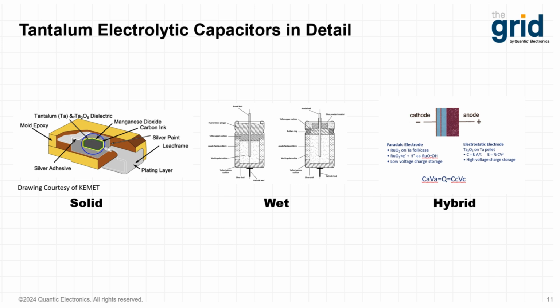However, there are some styles of tantalum capacitors that do offer much higher capacitance ratings, such as hybrid wet tantalum capacitors made by Quantic Evans. Now, these hybrid wet tantalum capacitors use a ruthenium oxide cathode. That ruthenium oxide has a really, really high surface area, which allows them to pack in significantly more capacitance in a volumetrically small space. These capacitors are capable of reaching up to 0.36 farads in a single compact package and a voltage range of 10 to 125 volts.